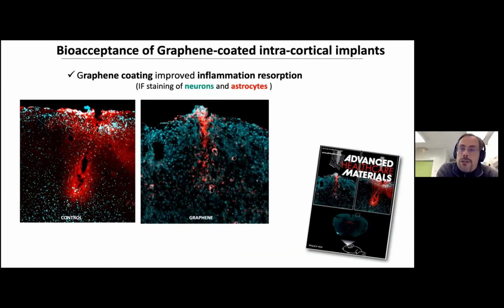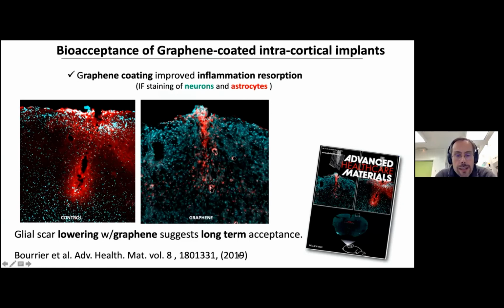So this bioacceptance can also be very useful for implants. And this is, for example, an intracortical implant for probing the activity of a mice brain. And this is the control with a commercial implant. And the same implant coated with graphene, and the red elements here, which are stained astrocytes, which are the hallmark of the inflammatory response of the brain, are much smaller in the case of coated graphene. That's quite important because it suggests long-term acceptance of graphene.